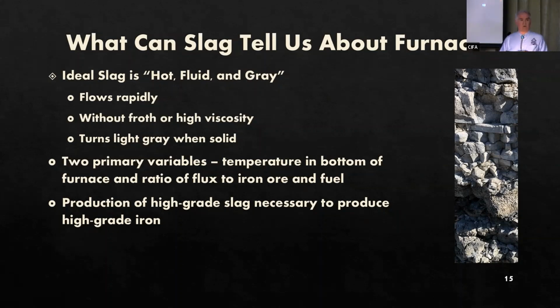The relative temperature was more important to these furnace workers than the absolute temperature, because that was something that they could control better. They gauged the relative temperature by looking through a peephole near an air inlet or a tuyere. And the slag temperature looking through there was estimated based on its color and its fluidity. Now, I don't know if you've ever seen inside of a hot blast furnace, but there's a lot of light streaming out of that little peephole. And so I admire the furnace workers for their ability to discern one kind of slag compared to another.